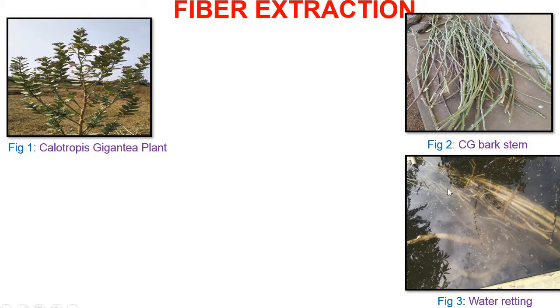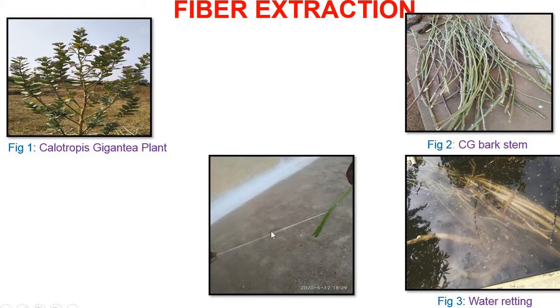After taking that bark stem, we will dip it into water for nearly 7 to 8 days. During those days, the water molecules, having capillary action, are able to penetrate into the stem. It will ooze out and get somewhat bulgy. After some 8 days, we will take out the Calotropis gigantea bark stem and keep it in sunlight for 2 days. After that, the fibers will slightly come out, and you can see in the figure how we extract the fiber in a mechanical manner.